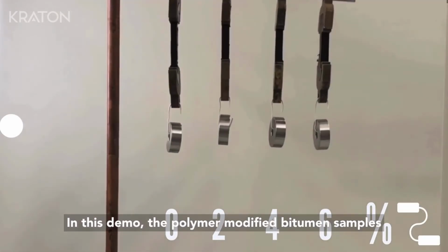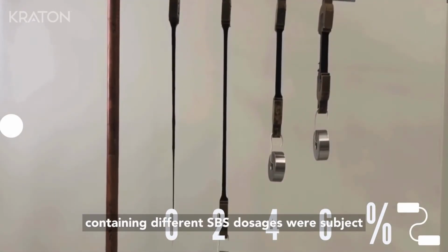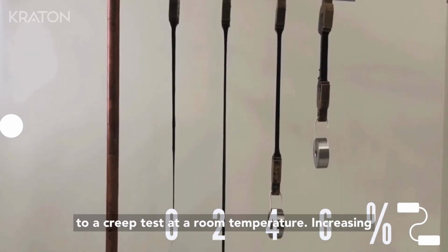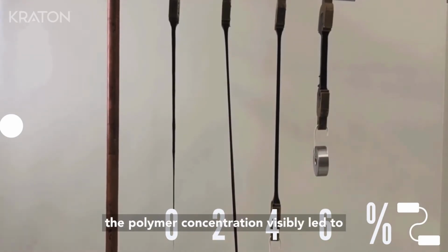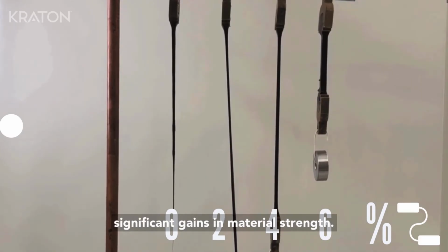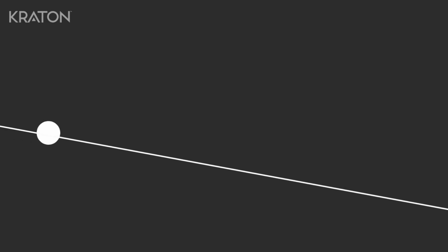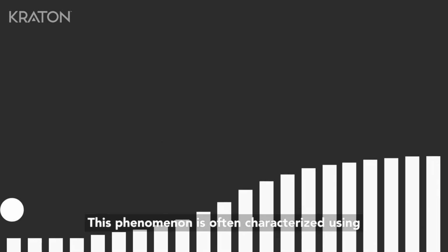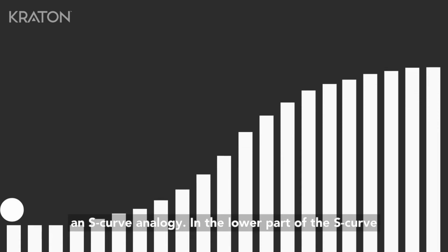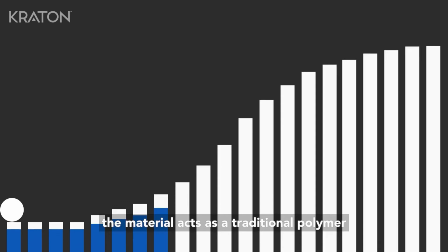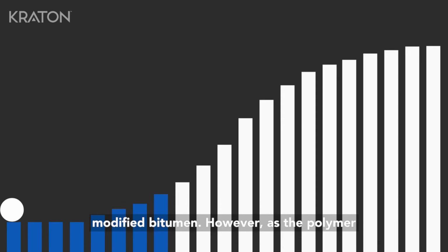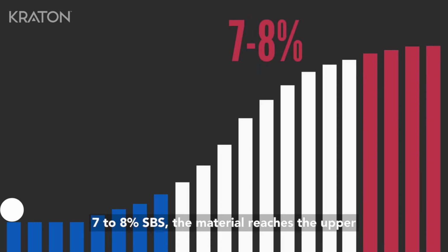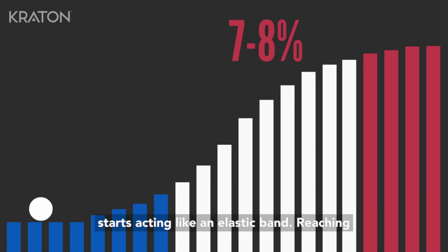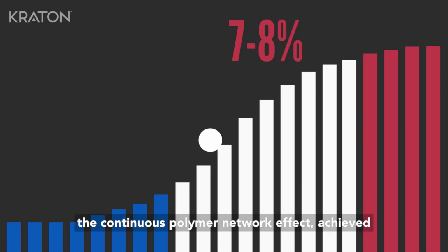In this demo, the polymer-modified bitumen samples containing different SBS dosages were subjected to a creep test at a room temperature. Increasing the polymer concentration visibly led to significant gains in the material strength. This phenomenon is often characterized using an S-curve analogy. In the lower part of the S-curve, the material acts as a traditional polymer-modified bitumen. However, as the polymer concentration increases to approximately 7 to 8% SBS, the material reaches the upper plateau of the curve. In that region, the material starts acting like an elastic band, reaching the continuous polymer network effect.